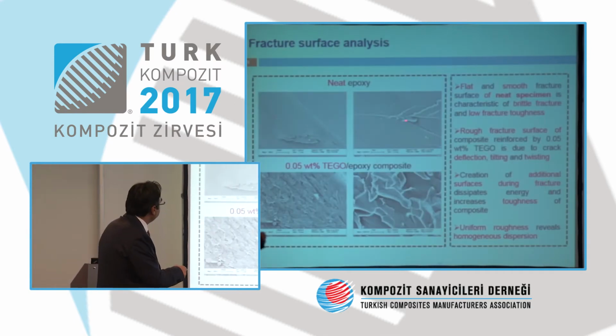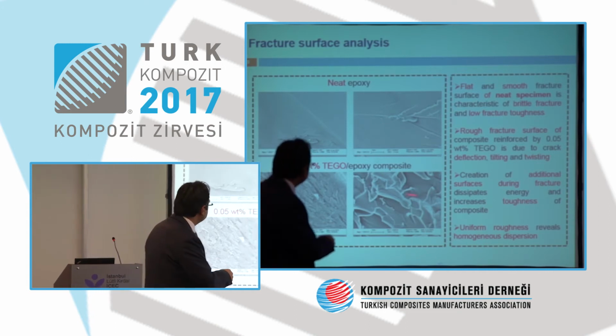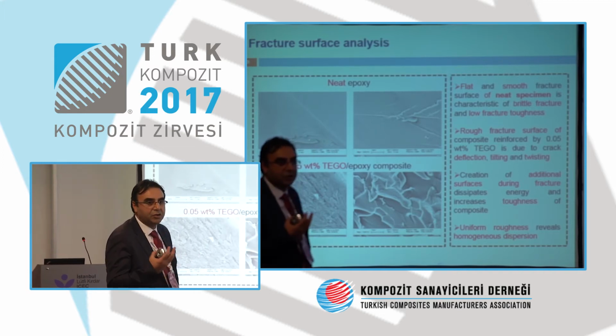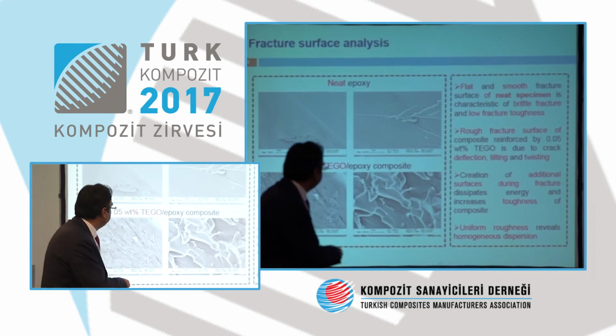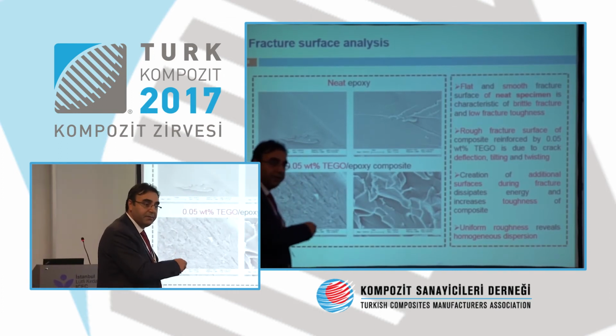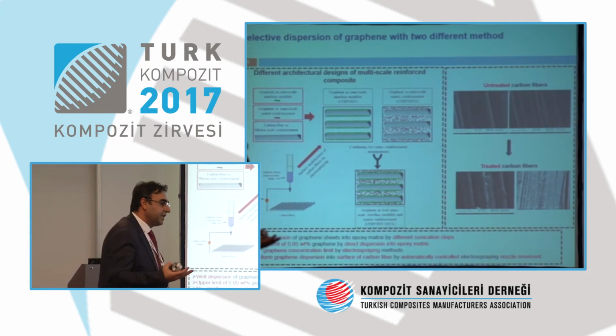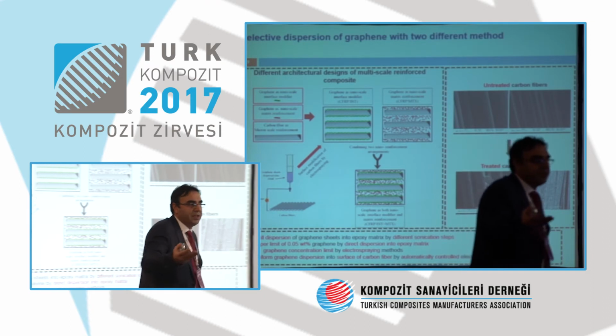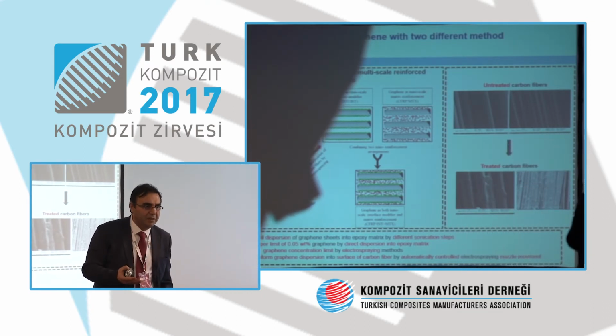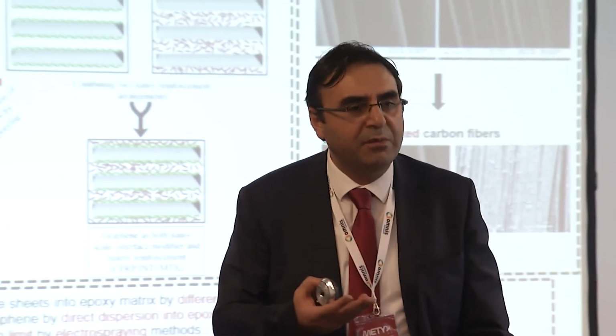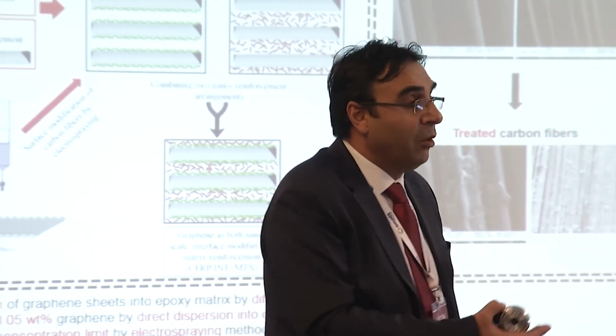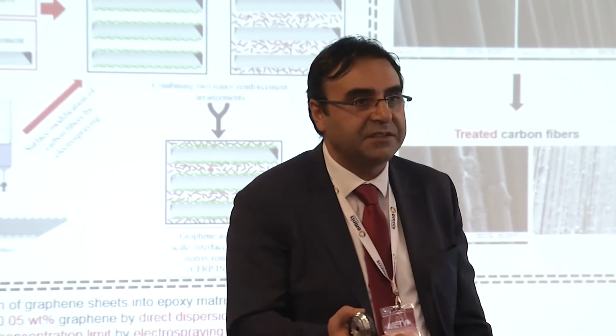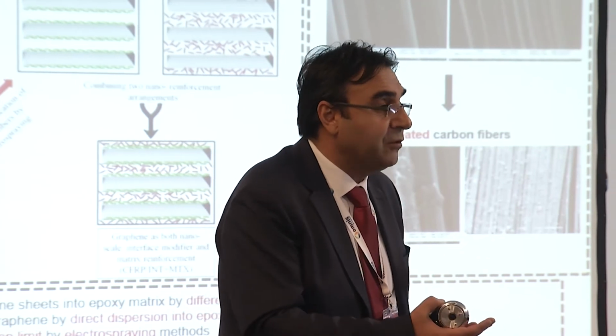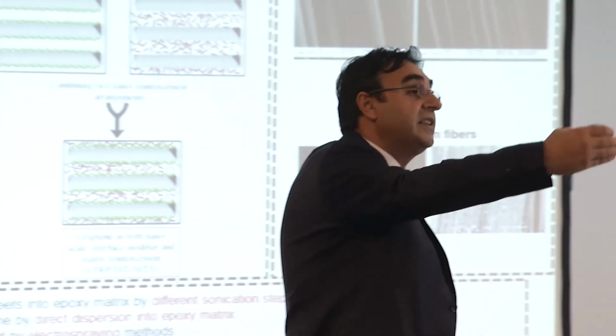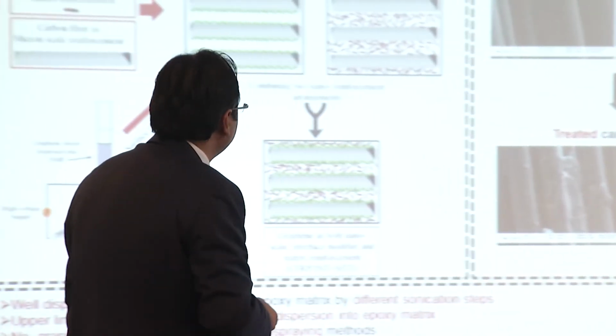And this is the neat one, and you see that it has a very clear surface, like your material is cleaved. And here, this is a very ductile fracture. Your graphene pins the crack propagation and increases the mechanical performance of the matrix. And we said that that is fine. This is what has already been achieved by people by adding different amounts of material. But our main interest is to increase the performance of the composite. That is very challenging, because you already have fiber reinforcements, either carbon fiber or glass fiber, which are very, very strong. You have to do really smart things so that the improvement will exceed the reinforcement that comes from the fibers.